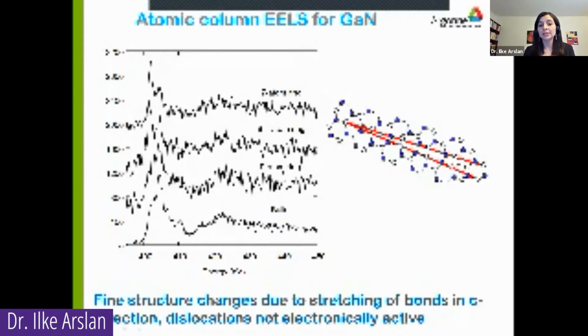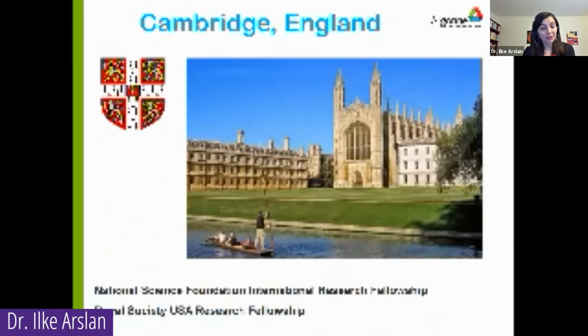And when that happens, that changes the bonding, and we can see that change through the spectrum. But the important thing is that there are no states formed lower in the band gap, which we also looked at with DFT calculations. And so these dislocations are electrically inactive, most of them, unless they have point defects or other things that segregate to them, which also can happen. So I spent quite some time looking at those.